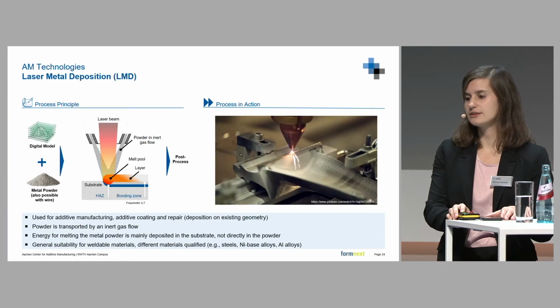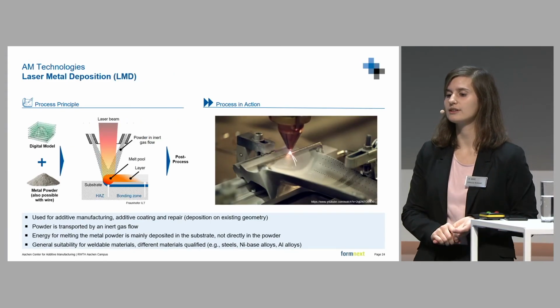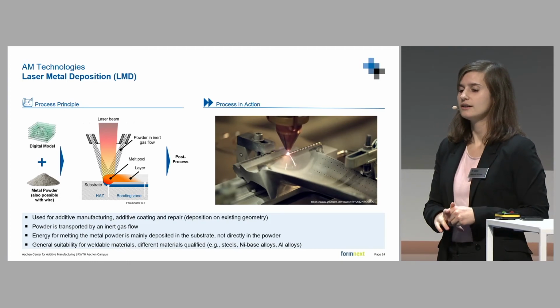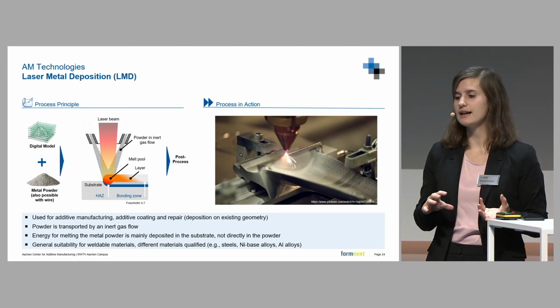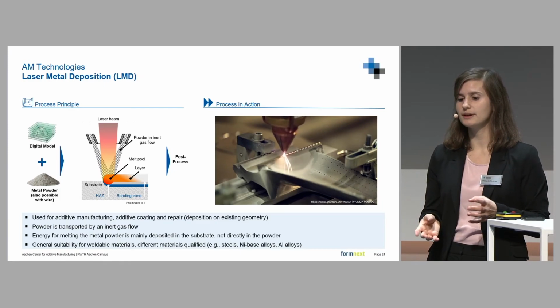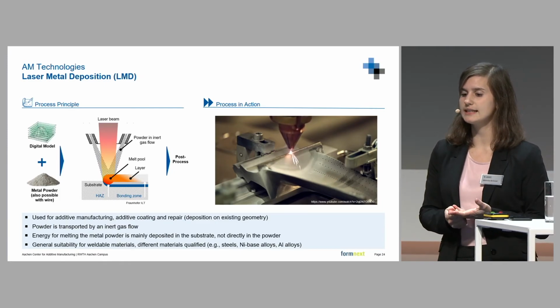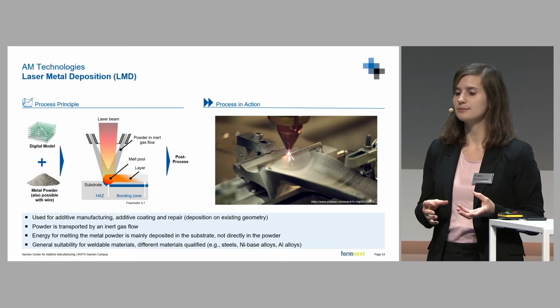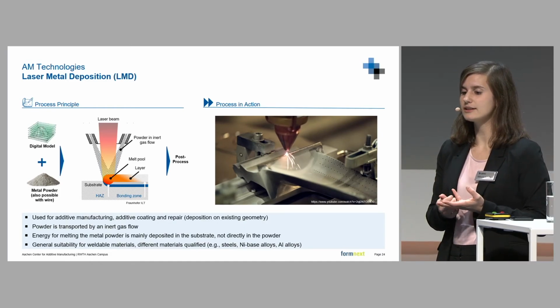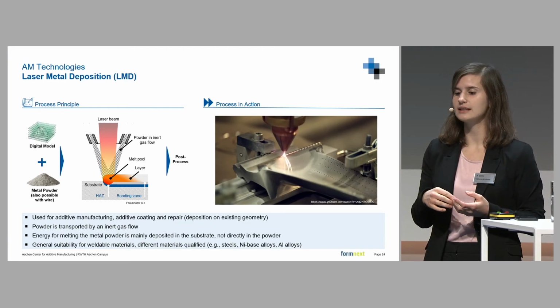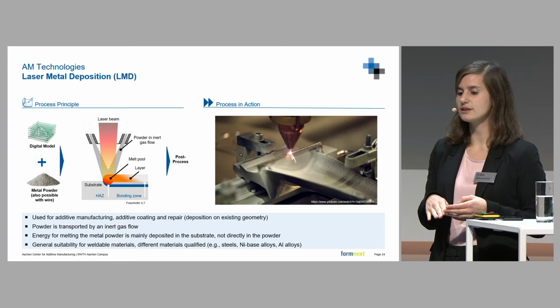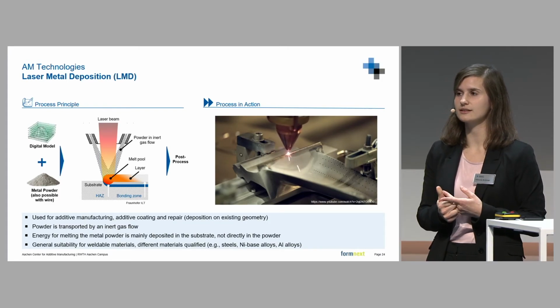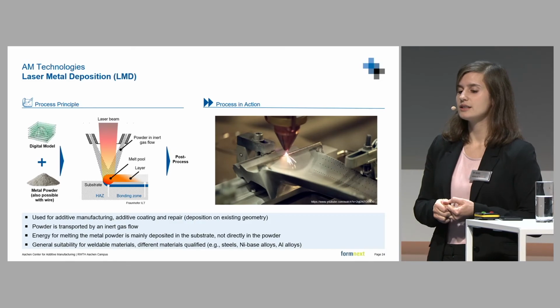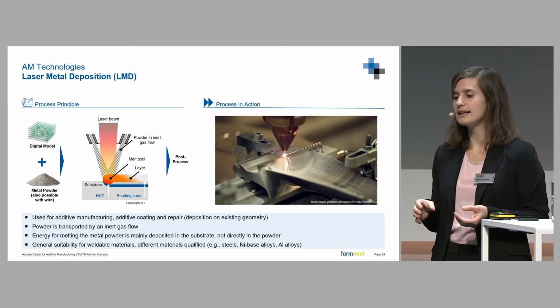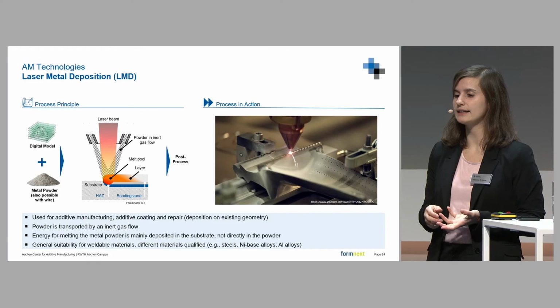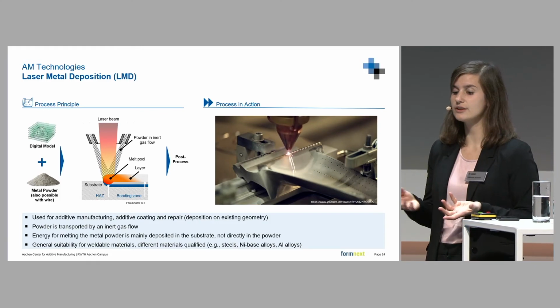All right, let's go into laser metal deposition, which process you can see on the right-hand side. Differing from laser powder bed fusion, you don't have a powder bed that's being fused, but you also have metal powder as input material and a digital model. The way it works is the powder is in an inert gas flow, and it gets put onto the substrate, and then it's successively melted. So you just apply the material with each layer that you're generating.